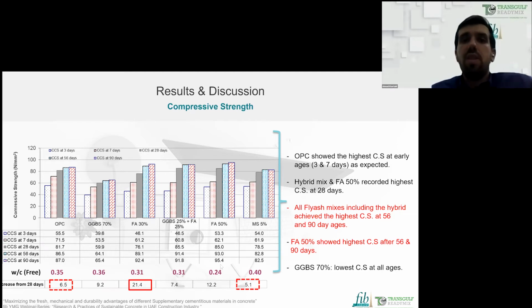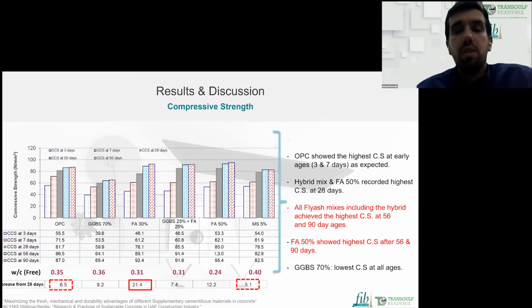It can be noted that at 50% fly ash, which had the lowest water demand, we maximize the strength in comparison with the Portland cement, and by far compared to the GGBS, because when we include 70% GGBS, the strength dropped, also because of the higher water demand compared to the OPC. The maximum strength, with the 420 cement content and a water cement ratio of 0.24, achieved 95 megapascal for the 50% fly ash. We are talking here about cube compressive strength for the whole study.